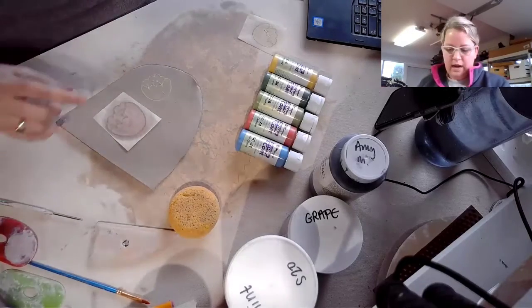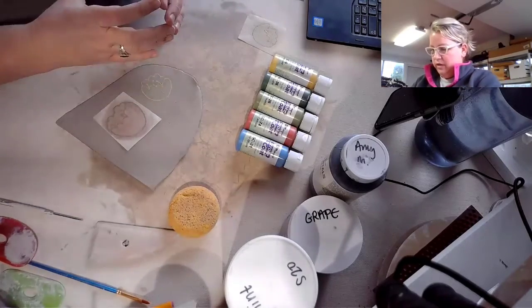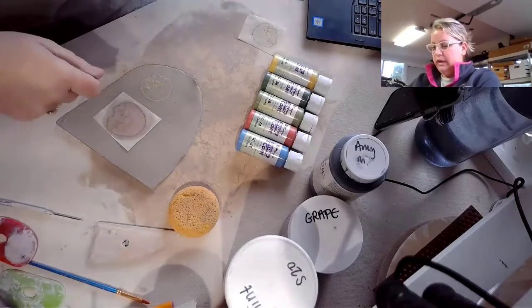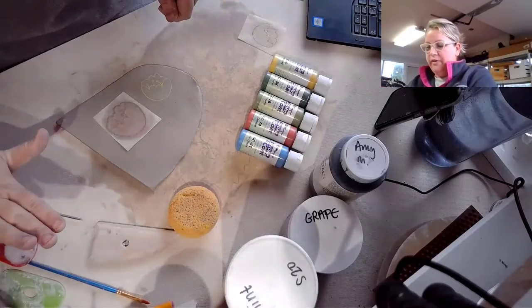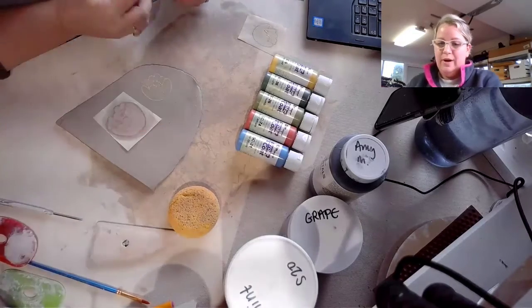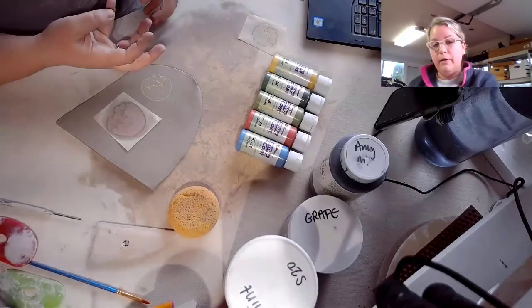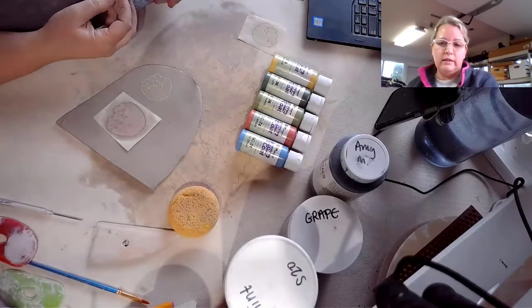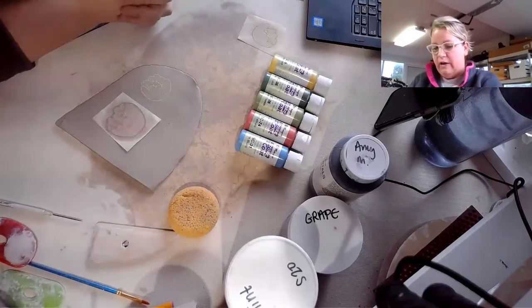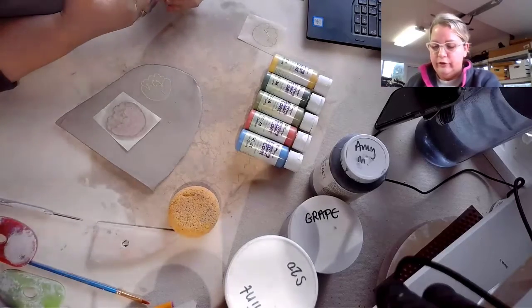So, then after this, you know, you could go in and add, you know, another transfer or leaf. I've done this technique with big, long sheets of newsprint. And if you don't, you know, almost like roll it on there and smush out all the air bubbles, the slip or the underglaze doesn't necessarily adhere to your wet slip or, I'm sorry, your wet clay that well. And so, that's where you might get the air bubbles underneath the slip or the underglaze and that's when things start bubbling and popping off. So, I have found that working in smaller sections like this has been more beneficial for me.